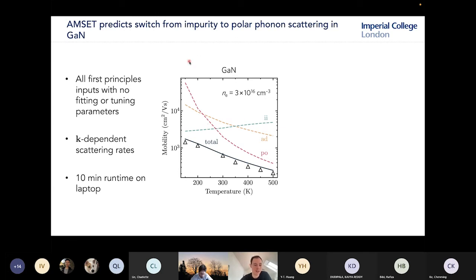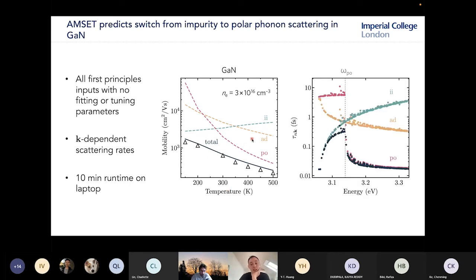This calculation I'm showing here was done, as I said before, using only first principles inputs. There's no fitting. And this entire calculation took about 10 minutes on my laptop once I had all the inputs. Just for comparison, if you wanted to do this using some of these DFPT approaches, that's going to take you tens of thousands of hours on a supercomputer to do a comparable calculation. And you actually get a lot of information.